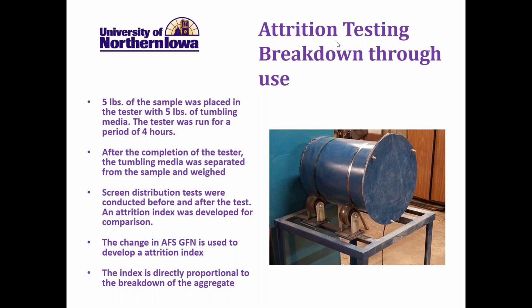Our attrition testing was based on what has been done historically in the Sand and Gravel Institute. The American Foundry Society does not have a breakdown or attrition test. We had to borrow someone else's. We did this by placing 5 pounds of the aggregate along with 5 pounds of ceramic tumbling media. After 4 hours, we would separate the tumbling media, and then test the sand in screen distribution.